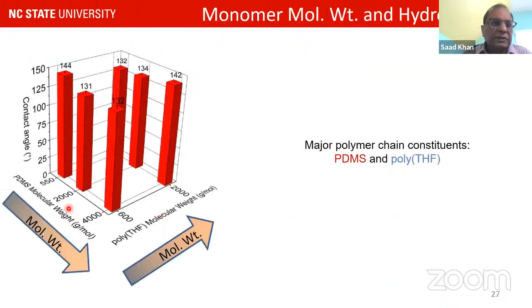So if you look at the two main components, one is the PDMS and the other is the poly-THF. You can see that as we vary the molecular weight, going high in this direction and high in this, the average contact angle on a cotton substrate is reasonably high. It's around 130 to 140. But it just changes depending on the molecular weight we use.